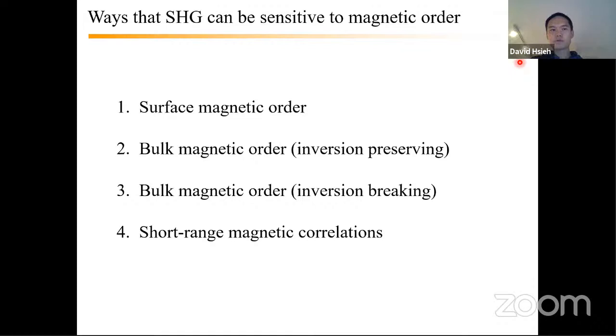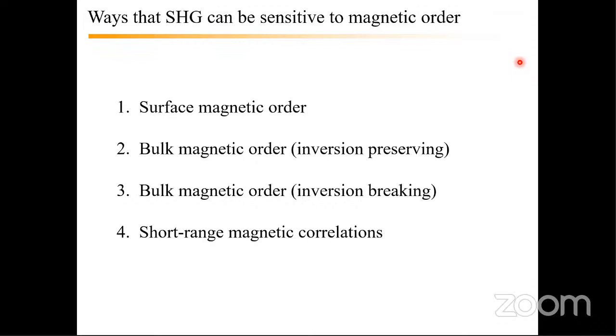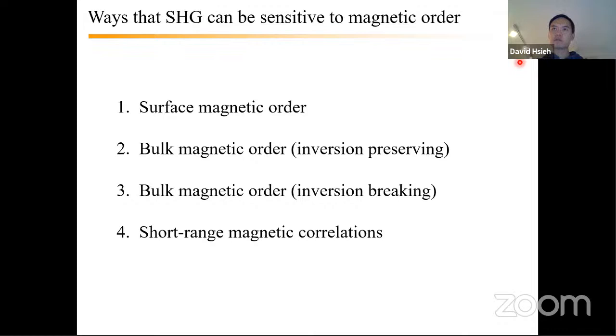But what's typical, when we get that small, we actually have issues with sample damage because it's so intense. And so typically we back off a little bit and we stay in the few tens of microns range. So when you see these anisotropies, you have to worry a bit about domains and stuff in the analysis within the beam. We do. Within the beam spot, if they're smaller than tens of microns, then certainly that becomes an issue we have to contend with in the analysis. Okay. Thank you. Yeah, thanks.